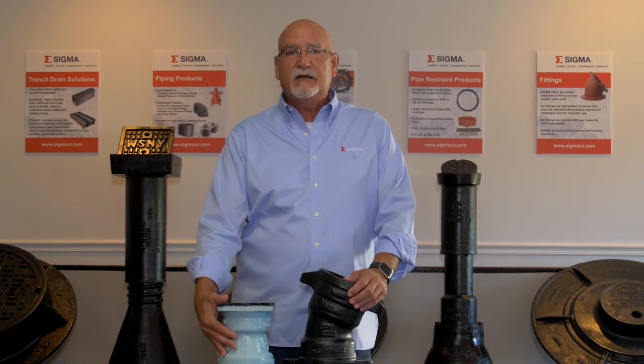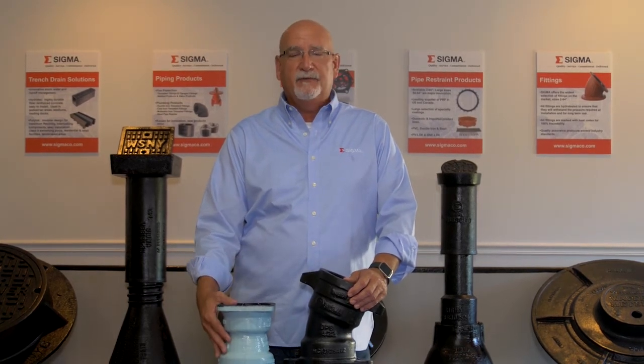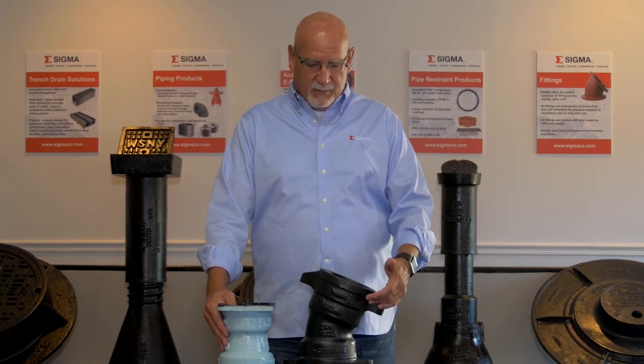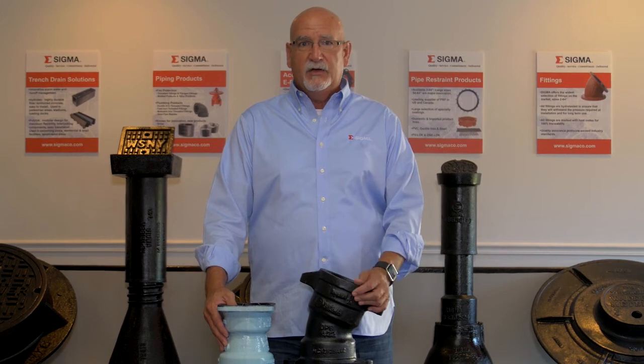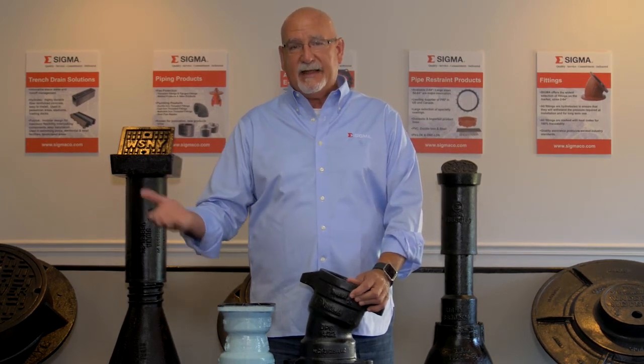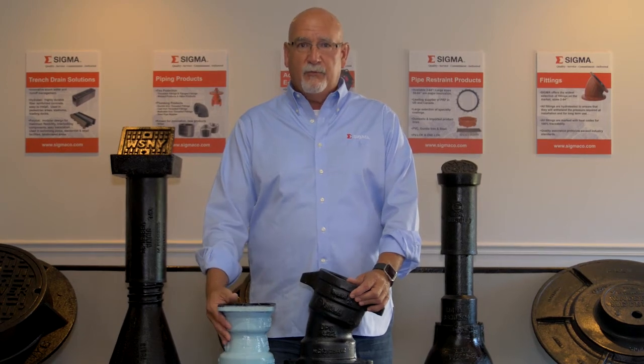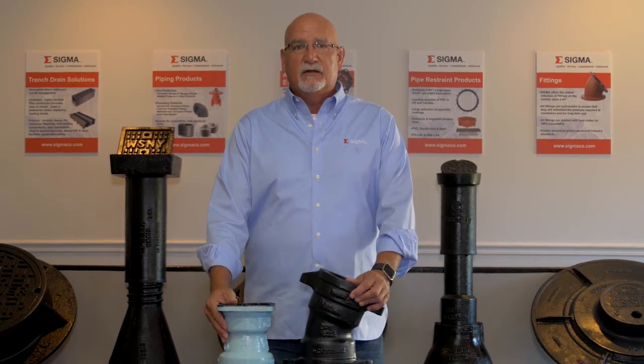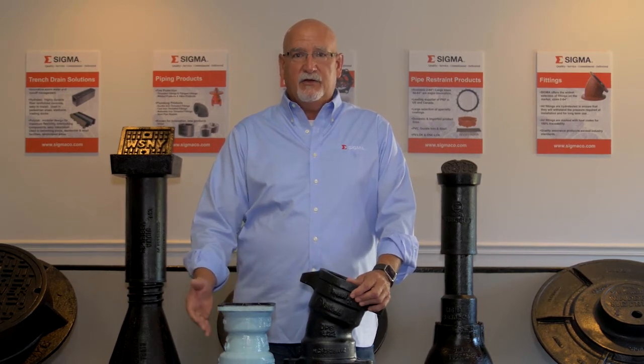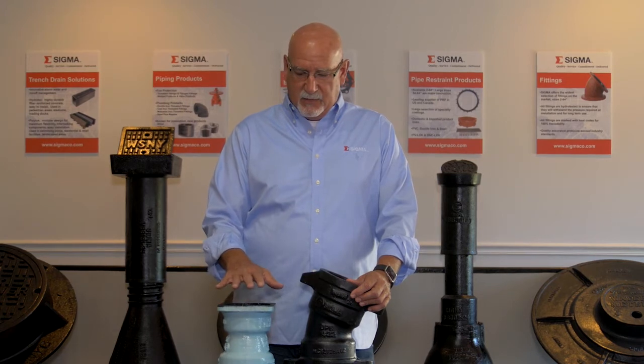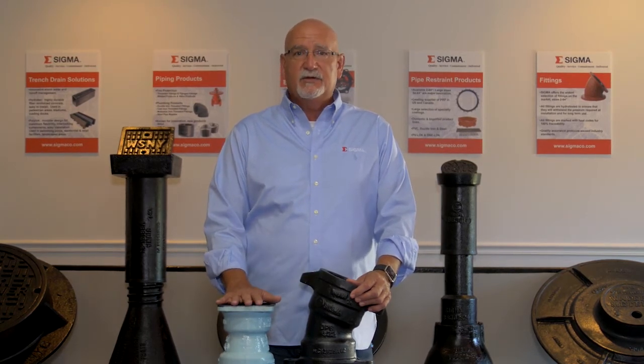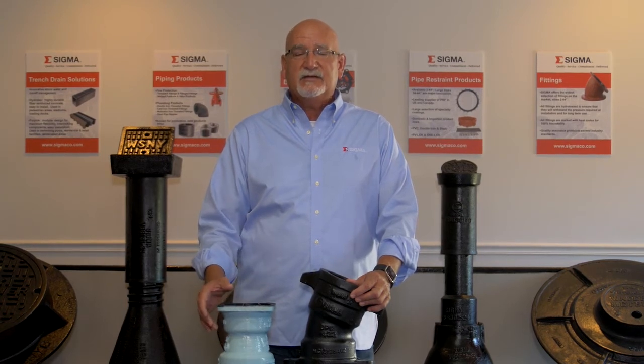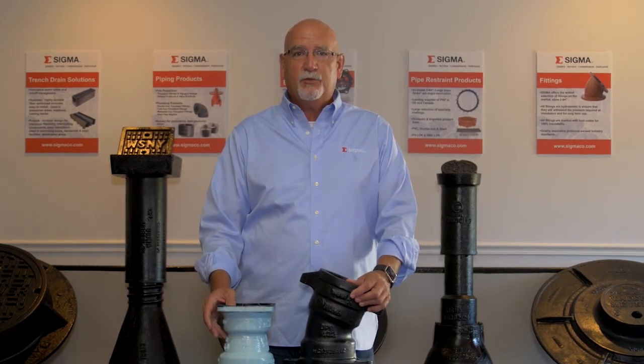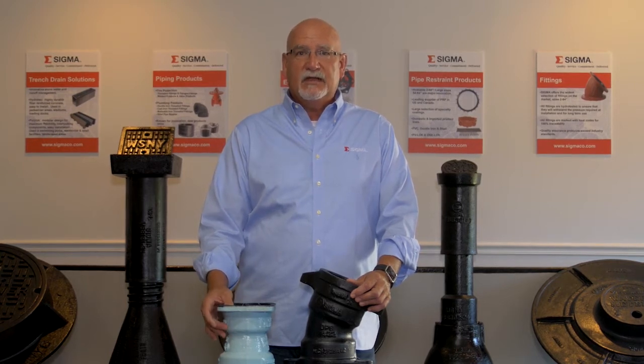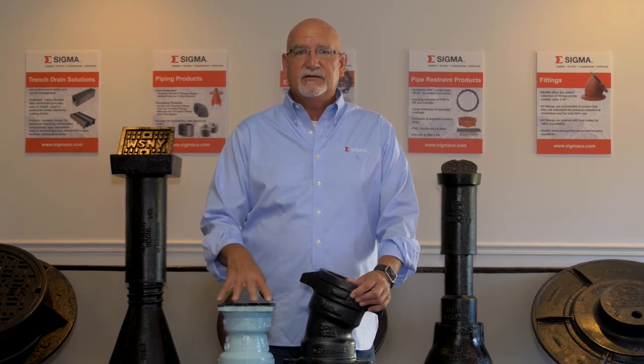So this particular fitting placed in the ground in a very difficult environment next to a bare fitting with black asphalt, a fitting with zinc and black asphalt, or FBE would perform better over the life of the fitting in terms of loss of mass due to corrosion than any other product we offer. This is the best coating that Sigma can offer for difficult environments. It is a zinc Tnemec sacrificial primer with a top coat of Tnemec material that provides us a barrier that is very, very comparable to FBE.